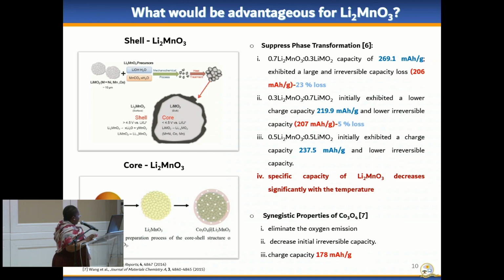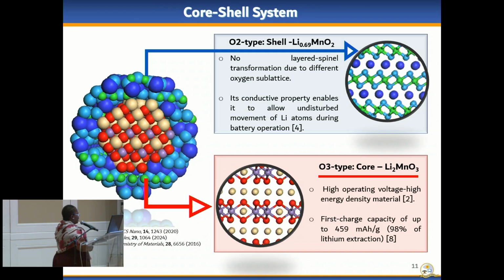And in terms of having it as a core, there were several good things that came out of it, where it eliminated the oxygen emission and also decreased the initial irreversible capacity loss. But the bad thing is that the charge capacity was then reduced to as low as 178 milliampere hours per gram. So in this study, we are looking into a new type of shell material, which is the O2 type material. And this is special in such a way that amongst the different lithium manganese oxide layer structures, it is the only one so far that does not undergo a layer to spinel transition. So we are going for this material to see if it can remedy the issues that I mentioned.